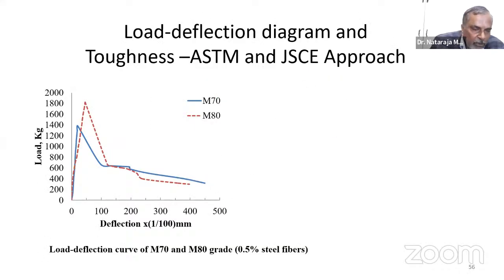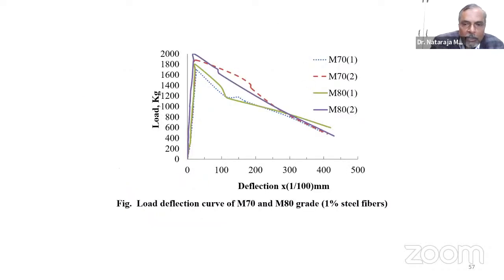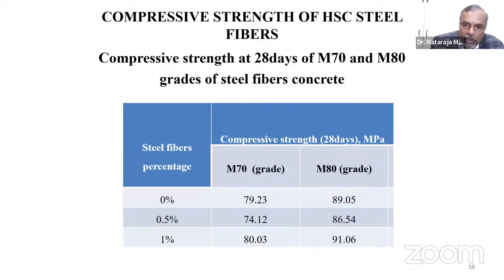So this is for 0.5% fiber. If you are happy with the toughness, limit it to 1%. If you still want an enhanced percentage of the fiber to be added, your area is further increasing. And all these area calculations you can do because we have the tools available at present, and the ductility of the concrete can be determined.